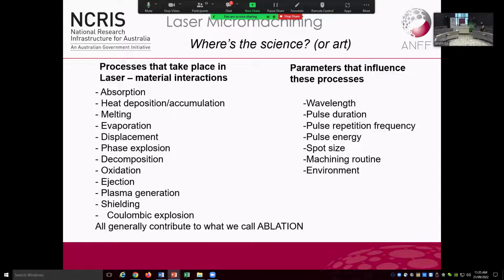Some of the more exotic stuff that happens is the last one I have there on the list, which is coulombic explosion. And this is something that's specific to ultra-fast laser processing, where you will actually exceed the work function of the material, strip out a whole population of electrons from it, leaving you with a positively charged plasma, which will then expel itself away from the surface, without putting a lot more thermal load into the material. And that's the sort of regime we want to be in.